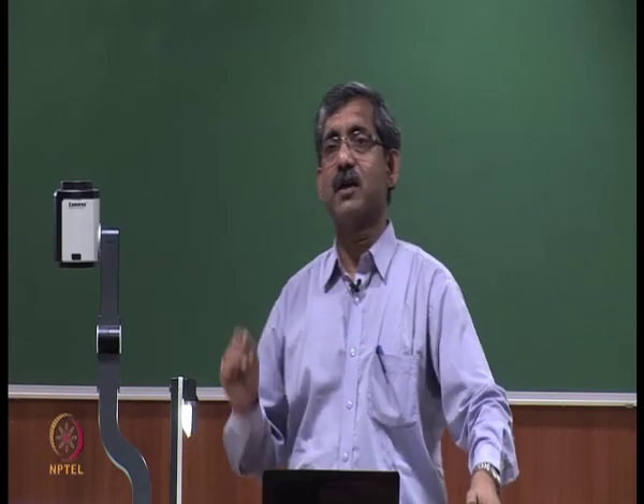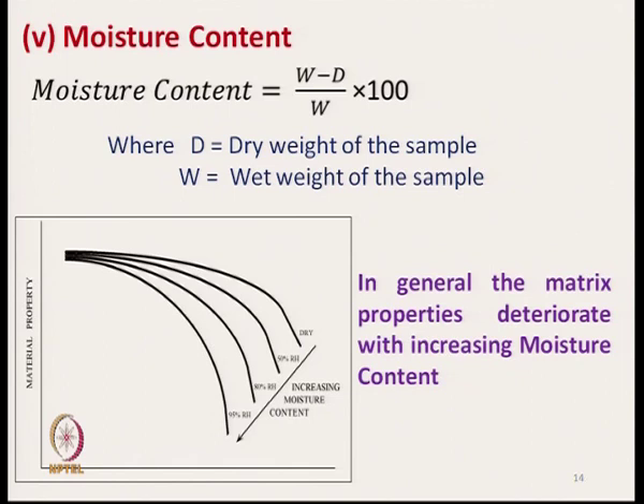Next important characteristic is the moisture content. We must know the moisture content of matrix material because it affects the characteristics of the matrix. In this picture we can see that as the moisture content increases, this is dry, 50% relative humidity, and this is 95% relative humidity. As the relative humidity increases, moisture content increases, so there is a drop in characteristics. There is a sharp drop in the material property. So material property in general reduces.